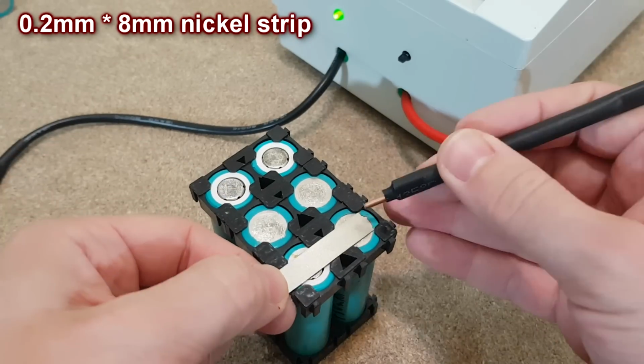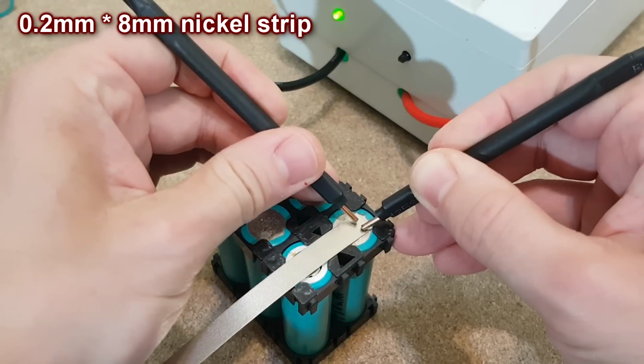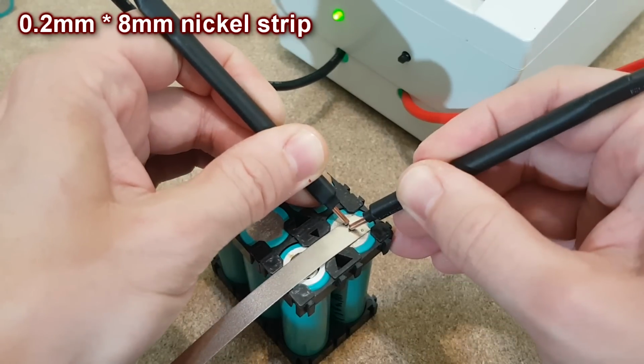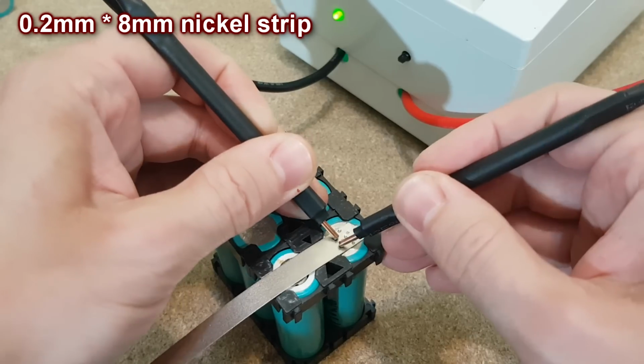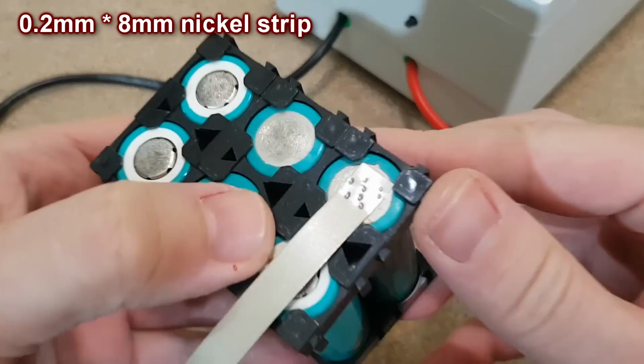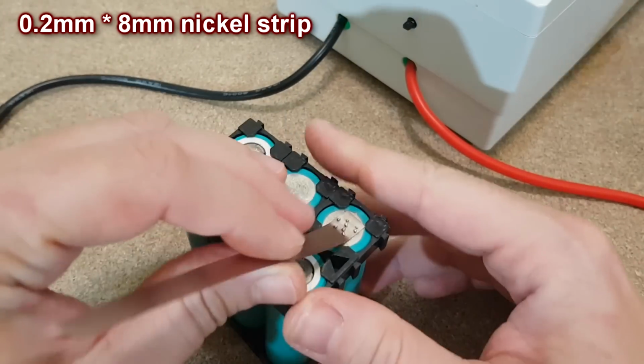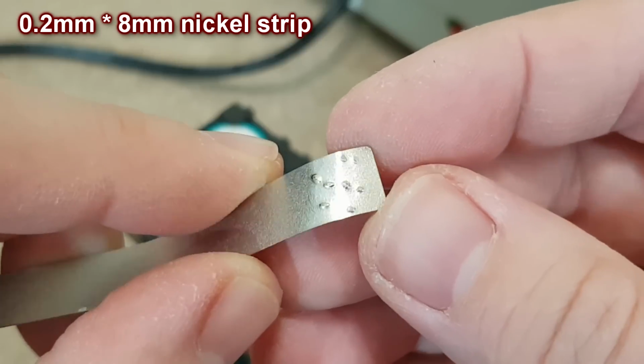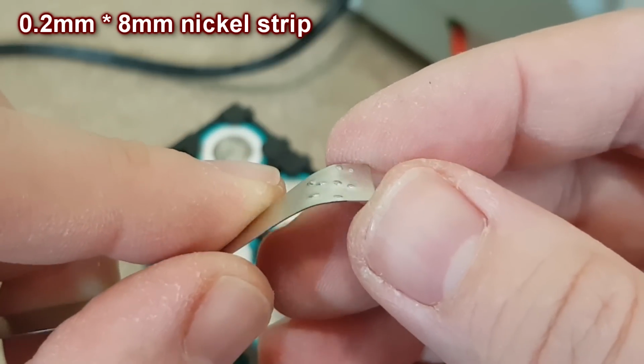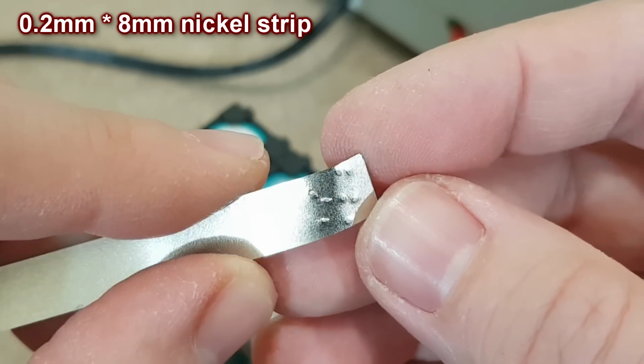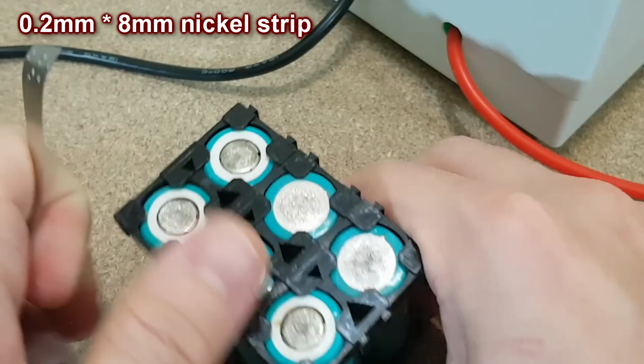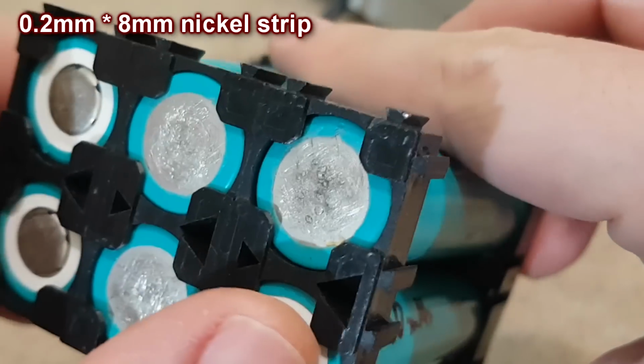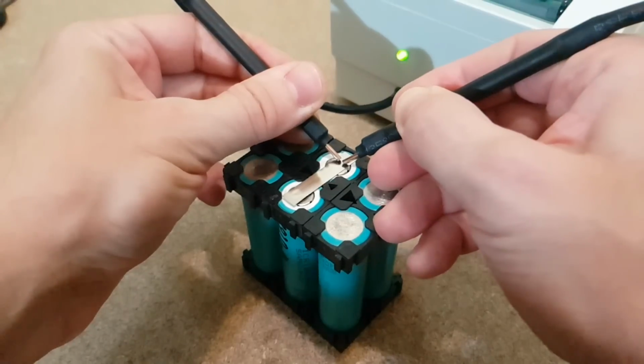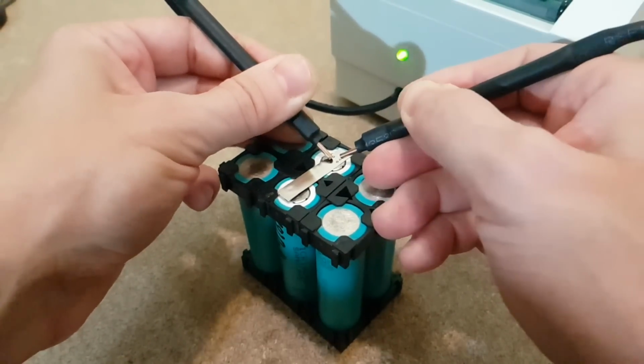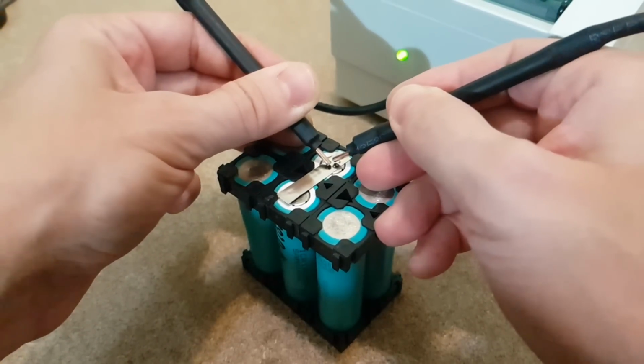This is a 0.2 mm thick nickel strip. What, you don't think it will work? You are right, the welding points are very weak. In my opinion, the best results are with nickel strips with a thickness of 0.1 or 0.12 mm. But let's make a battery pack using 0.12 mm nickel strips.